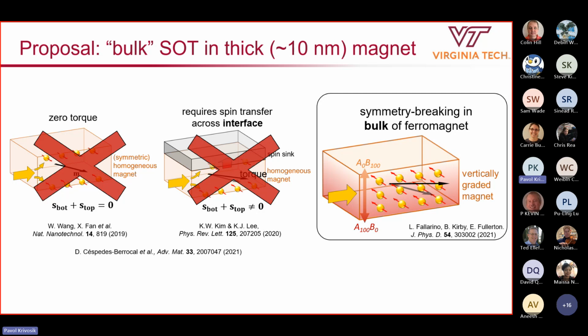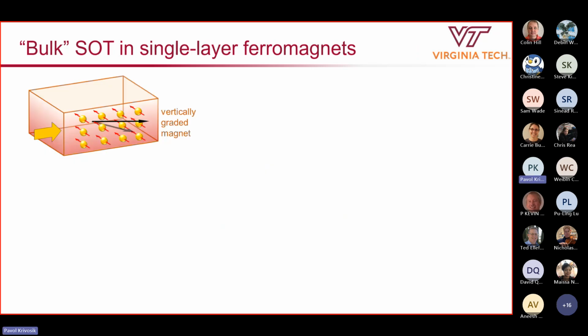Now we can achieve this kind of asymmetry, for example, by intentionally varying the chemical composition in the ferromagnet. Right. So we call this a vertically graded ferromagnet. Okay. And again, in principle, with spin accumulation arising everywhere within the ferromagnet, we ought to be able to generate a torque, again, without having to transfer excess spins from an external material. Okay. So that's the idea, and we like to say that this was the original idea, but in truth, it was not.